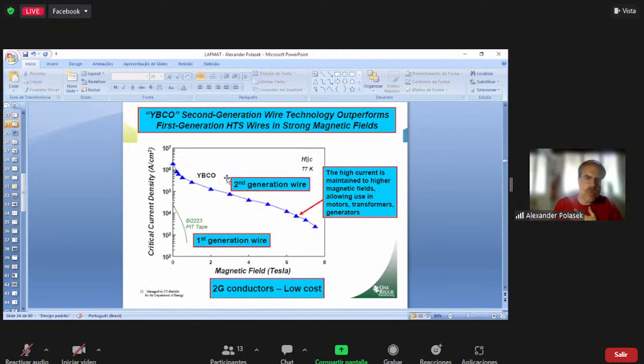Oh, here is a comparison. Why am I talking a lot about second generation tapes? Because as compared to first generation and to all other superconductors, even the low TC and MgB2, YBCO is the material that has the best behavior under high magnetic fields. You can see here the critical current. Normally it decreases with increasing magnetic field, but you can compare. You can see that this decrease is not so fast in YBCO as in BSCCO-based superconductor. And this was at liquid nitrogen temperature. If you have liquid helium temperature or lower temperatures or another cooling method, you can have even better performance.